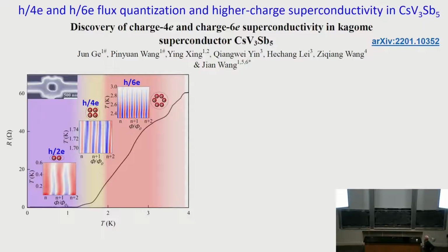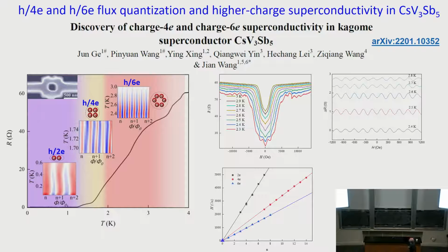Okay, so this is my last transparency on CVS. Let's see what they observe. They see flux oscillations, 6e oscillation, just going down from the mean field transition, then 4e, then eventually 2e, all right? So what do they see? Let me show you here. These are the oscillations, with background subtracted. I'm only showing you the 6e data here at the highest temperature. You take this minimum, you put it on this plot, the 6e. At lower temperature it becomes 4e. At the lowest temperature, it's 2e.